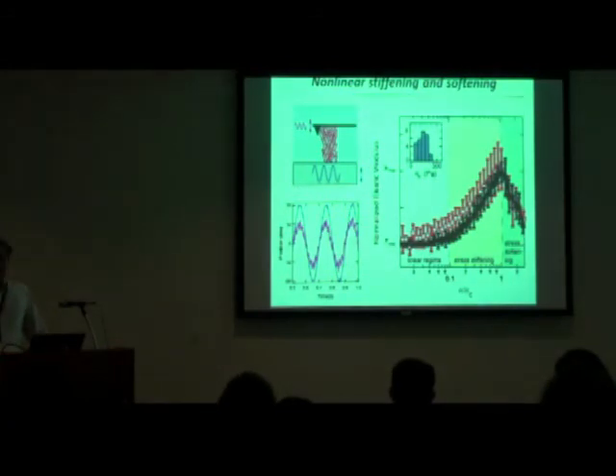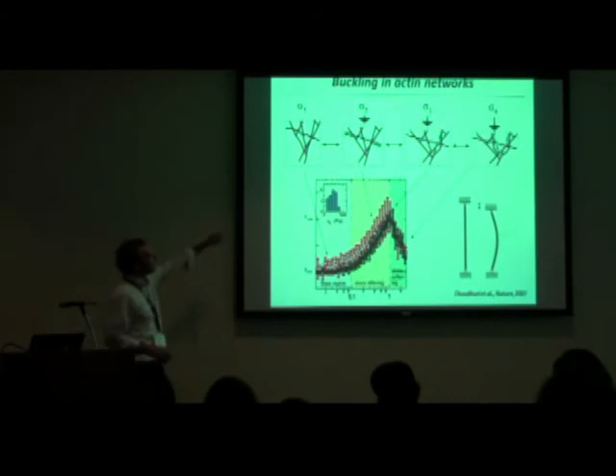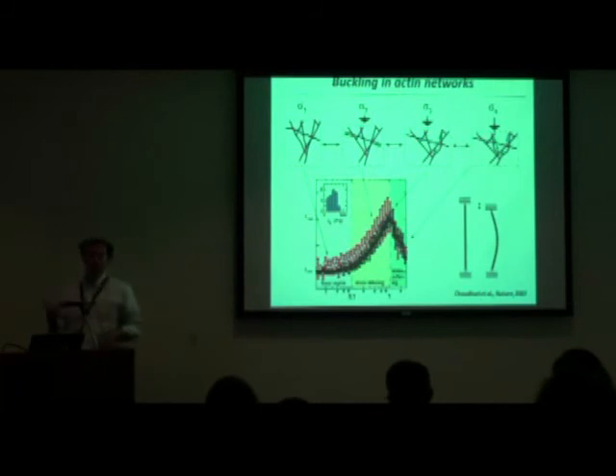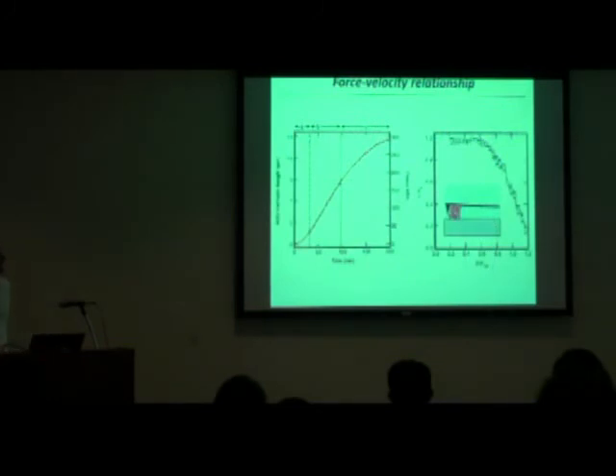We can look at its elasticity, and we did this a couple years ago to show that the elasticity is quite complex. There's a nonlinearity to both the stress stiffening, and there's a softening behavior that we attributed to buckling of individual filaments. So the elasticity of these networks is unique, and the buckling process results in a reversible stress stiffening. That is reversible in which if you let the stress off, the network recovers its elasticity, and you can go right back to its original elasticity. So other than the mechanical properties, it's really the dynamic properties I want to tell you about.